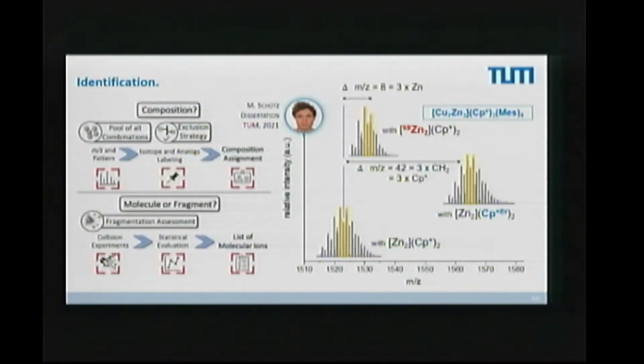That means, since we need a resolution of ±1 hydrogen atom, with high precision, we must rule out all coincidences of overlaying masses and so on. And we do that by a double labeling. We work with 68Zn labeled zinc. You can buy 68Zn labeled zinc metal. So I must make my students buy 68Zn labeled zinc foil, then do all the chemistry to make the zinc chloride and then the zinc Cp*. You can imagine this is work.